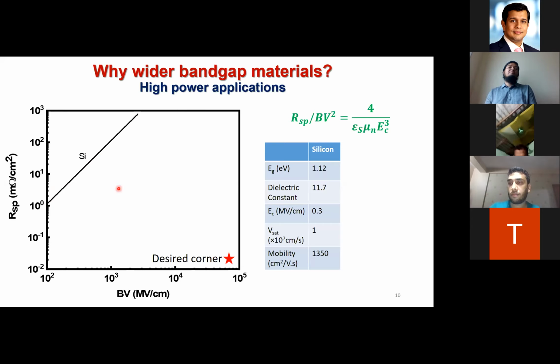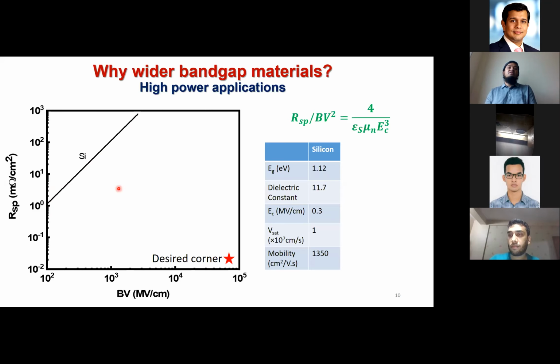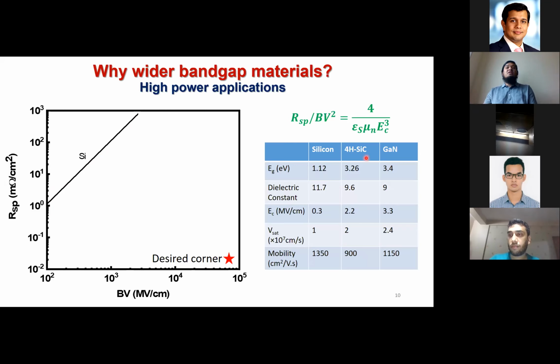So what if we try to replace silicon with another semiconductor that has a wider band gap? Take, for example, two popular wide bandgap semiconductors: silicon carbide, which has an energy bandgap of 3.2 electron volts, and gallium nitride, which has a wider energy bandgap. In a semiconductor, if we increase the energy bandgap, the critical electric field where the semiconductor breaks down also increases. So in silicon, we have a critical electric field of 0.3, but in silicon carbide and gallium nitride, we have 2.2 and 3.3.